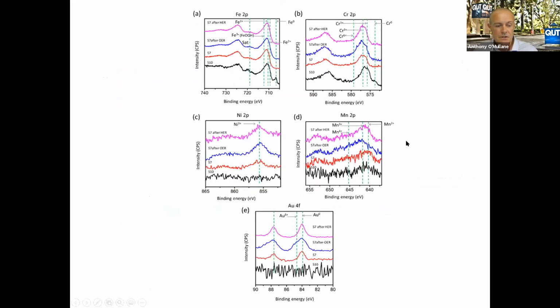If we look at the surface composition by XPS, on the initial stainless steel we obviously don't have any gold. Once we do our modification process, our gold comes to the surface. Then after we do oxygen evolution and hydrogen evolution, we don't see any change in the composition of our catalyst, which is quite interesting. What we saw before is that after the oxygen evolution reaction, we get significant compositional changes at the surface. Whereas here, with the gold present and with the chromium present, it mitigates against severe oxidation of the species on the surface.